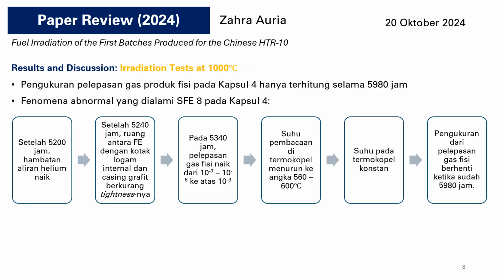As mentioned before, there was an abnormal phenomenon that happened to capsule 4, and here is the phenomenon. After 5,200 hours, the helium flow resistance increased, and after 5,240 hours, the tightness of the space between the fuel element and the internal metal box and graphite casing decreased, and also the gaseous fission product release was raised from 10 to the minus 7 to 10 to the minus 3 after 5,340 hours.